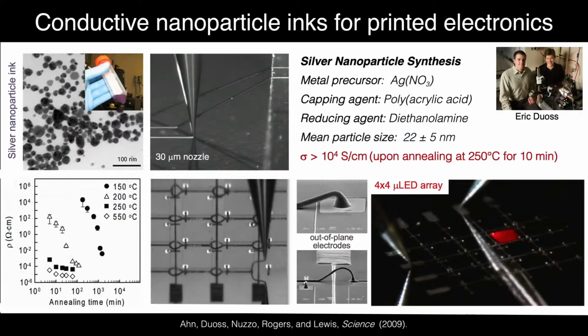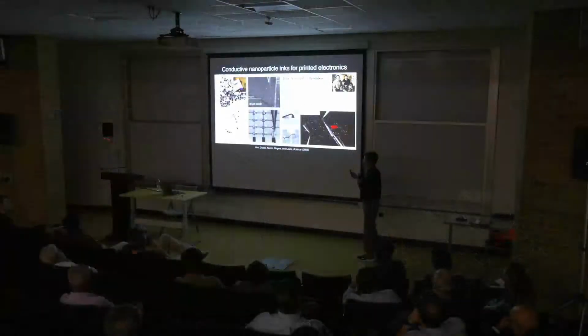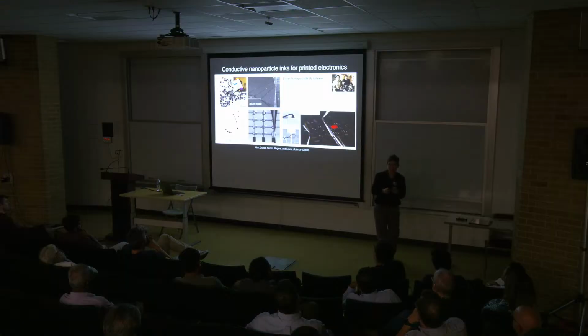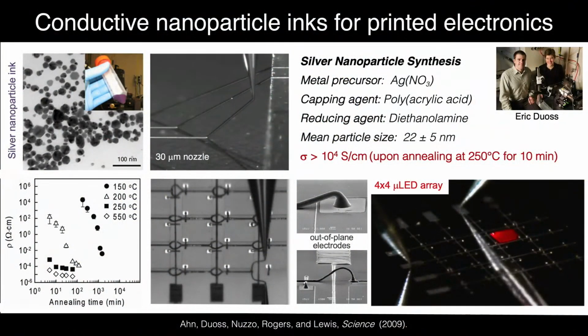They're not slumping. And that really led to the work that I'm showing here, which is a collaboration that we were very happy and fortunate to have with John Rogers at Illinois before I left. And you can see that this is actually a nozzle that's translating, coming out of plane and up to a step ledge. And we can use this then with these silver nanoparticles now. So we're replacing silica both with a smaller size particle and a functional particle, a highly conductive particle. We're still coating with polyelectrolyte, and we're able to induce this viscoelastic response in such a way that we can span gaps and create these electrode arrays in a planar configuration to wire up micro LEDs.